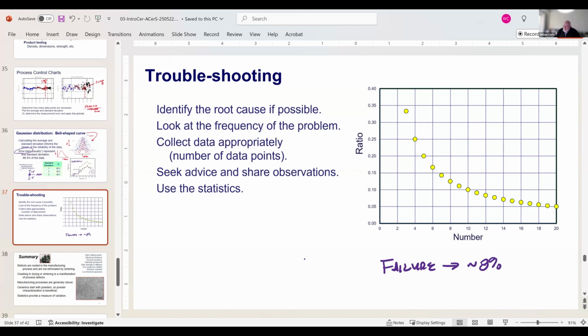And in the discussions, I came back and I said, how are these made? And they said, oh, they're made by slip casting. And I said, how many plates do you cast out of a given batch? And they said that they cast 12. And you go to 12 here, and what you see here is this is 8.3%, right?